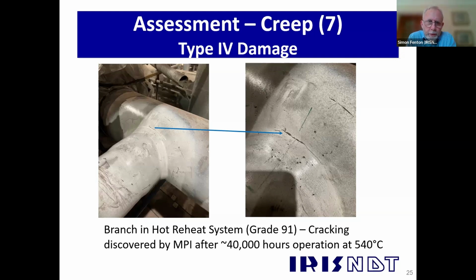So what we needed to know in this case was what was the damage mechanism. Looking at that macro crack there, the possibilities are, it could be a reheat crack, it could be a creep crack, or it could be a fatigue crack, any of those possibilities. So we used metallographic replicas to determine what we were looking at.